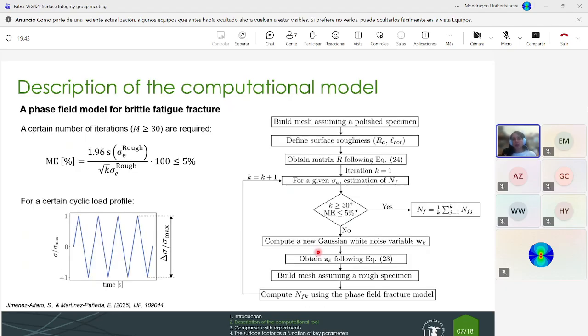Then here you have how the computational framework looks. We start by building the nominal surface, meaning we don't consider any surface roughness at this moment. Then we consider a certain combination of parameters, average surface roughness and correlation length, or root mean square surface roughness and correlation length, and we obtain the autocorrelation matrix. Then we start an iterative process. For a certain Gaussian white noise variable, we obtain the distribution of the height of the peaks, and then we build the mesh, assuming that we have a rough specimen. So we just introduce this height deviation in the nominal surface.